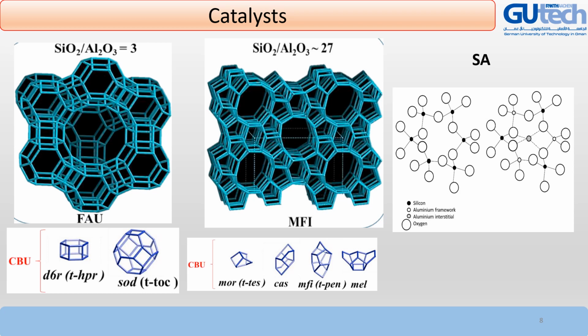The catalysts which are used in this pyrolysis system are based on silica and aluminum. The ratio of silica to aluminum, SiO2 to Al2O3, is between 3 to 27, and there are different types of catalysts that can be used. It depends on the products of the pyrolysis.